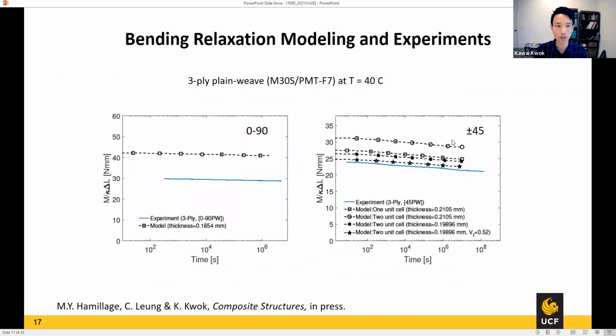And this is a comparison of the modeling and experiments that we collected and summarized in a paper that should be coming out soon. This is particularly for thin-ply plain weave. M30S is the fibers, and that is the matrix that we're looking at, and we did this column bending relaxation test. Basically, we imposed a certain curvature and fixed it for some time. So we'll see that the bending moment will relax over time, and that is what we want to capture, because that's what we compute from the mechanics model. We do this at several temperatures again, and then combine them into a master curve, which is what we are showing here for two different scenarios.